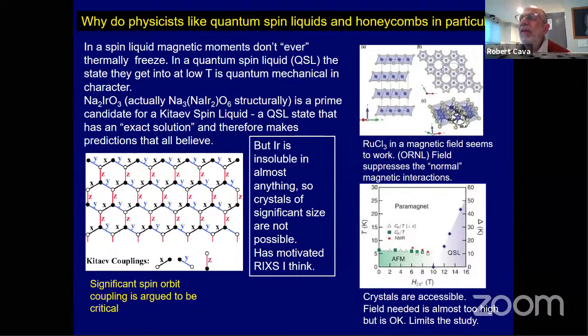I guess the original experimental work, at least, was on Na2IrO3, which is a very difficult material to make or work with. And from an experimental perspective, if you want to work on a honeycomb lattice with strong spin orbit coupling to give you some kind of magnetic interactions that you can get a good model for, you can't grow crystals that are very big. So all the iridate crystals that are known of this Na2IrO3, which if you remember from 10 years ago when that first appeared, they are sub-millimeter in size. So you can't really do good experiments on that material.